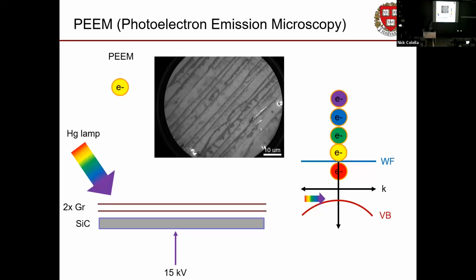it out. This is a picture of that same graphene thing as we were looking at before. These silicon carbide's got little ribbons of graphene growing on it. We're seeing contrast between the silicon carbide and the graphene. Spatial resolution in this is not as good, but it's a totally different physical mechanism. So what do you want?